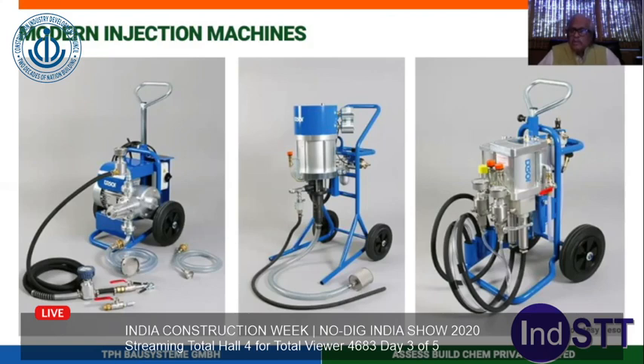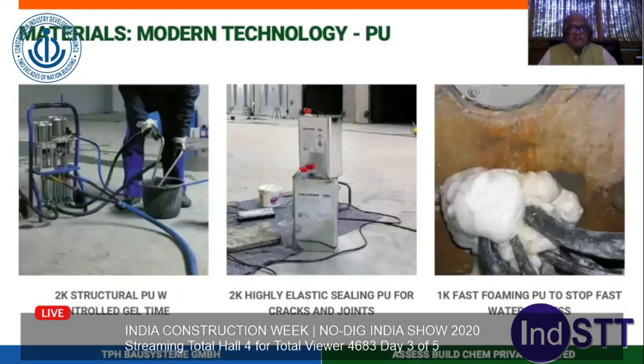For example, when you have a very small pot life injection which has to react with each other within say a minute or less than a minute, or even a few seconds, like 10 seconds, then you need 2-component machineries. You cannot put both the materials in a one-component machinery. So you necessarily require two-component machineries. Now these 2-component machineries, when you use polyurethanes, are sensitive to moisture. So these machineries should be designed so that no moisture is penetrating.